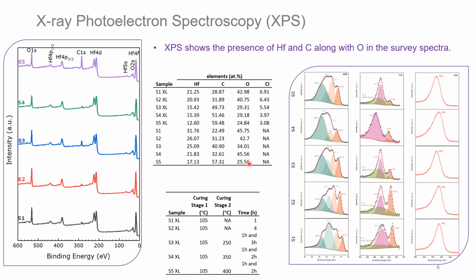XPS spectra show the increase in carbon and also decrease in oxygen for these S3 to S5 samples compared to S1 and S2. This indicates that curing temperature plays a significant role in the composition of the final ceramics, as the presence of moisture and oxygen largely depends on these temperatures.